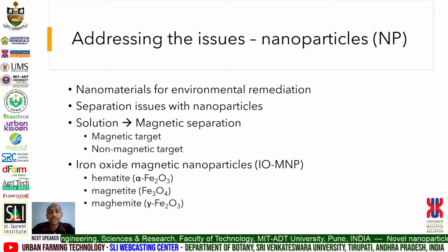Many reports on the use of nanoparticles like titanium dioxide, silica, silver, and even iron oxide itself are available in the literature. However, the use of nanoparticles in its free form in the open environment may not be the best approach. It will be difficult to recover the spent or used nanoadsorbent material, and it's not going to be feasible to remove nanoparticles by filtration or centrifugation. Magnet separation techniques have received considerable attention to address the separation problem.